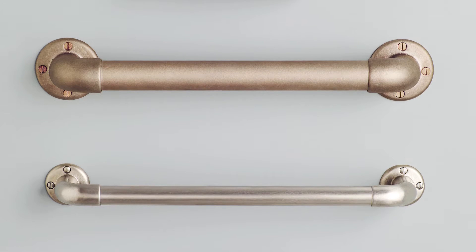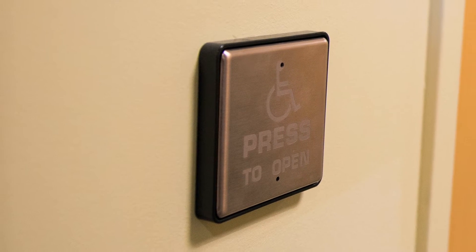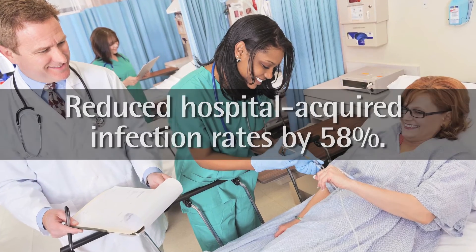Hospital-acquired infections — an issue so big that in 2008, the Department of Defense sponsored a study testing the ability of touch surfaces made from copper-based metals to reduce these infections. Conducted inside the intensive care unit of three U.S. hospitals, the study proved that copper surfaces kill potentially deadly bacteria, including superbugs, and reduced hospital-acquired infection rates by more than half — by 58 percent. It was a stunning revelation that something so prevalent and easily obtainable could have that dramatic of an impact, when you've got all sorts of chemicals that don't have near the efficacy of something that's been with us for so long. It was really exciting to realize we could do something fairly simple to implement and have such a dramatic impact.